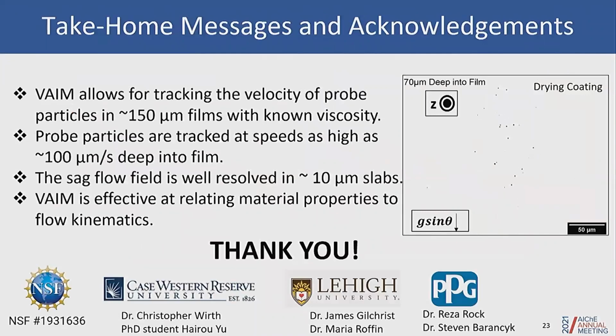So with that, I would like to give some take-home messages and acknowledgements. VAIM allows us to track the velocity of particles in a film about 150 micrometers thick with known viscosity. And these probe particles were tracked at speeds as high as about 100 micrometers per second. The sag flow fields were well resolved in a 10 micrometer slab. So finally, VAIM is very effective at relating material properties to flow kinematics.